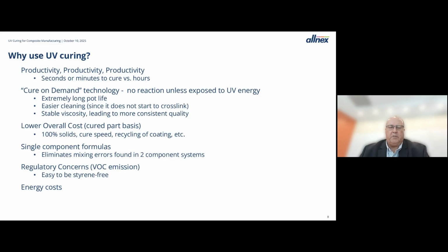We find from our customers that if you compare things on a cured part basis, UV can often have a lower overall cost. Part of that is it's 100% solids, the cure speed is very high, and you can recycle material if it hasn't been exposed to the UV energy, so you can reuse it. Mentioned before, these can be single component formulas, so you don't have mixing errors. There are fewer regulatory concerns. It's very easy to make these styrene free. And finally, the energy costs for UV lamps are generally lower than for ovens, and with the shorter cure time, you're generally using less energy to cure with UV than you would thermally.